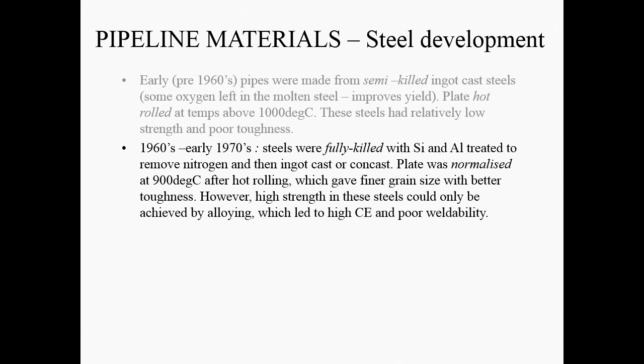The plate is then normalised after hot rolling. So you hot roll at 1,000 degrees C before, and you then heat to 900 degrees C and cool in air. And that's what normalising is, making sure that the steel is above 900 because you want it to be a single phase austenitic steel at high temperatures, and then cooled in air to transform to the room temperature microstructure. And we'll talk about what these are later on. And what that does is it gives very small grains in a polycrystalline steel, much smaller than the hot rolled structure.